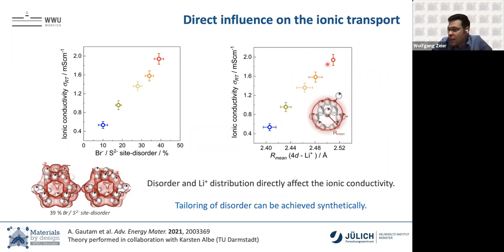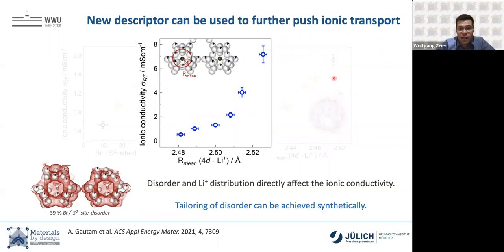And I was actually baffled by this, because oftentimes, at least in our community, we have the issue that one group may synthesize an ionic conductor and another group can't really match these ionic conductivities. And this happens to everyone. And the reason clearly is that even small changes in the synthesis procedure, be it that you didn't map out your furnace, or that the ampule that you reacted wasn't right in the middle, but maybe 5 centimeters out, so your actual synthesis temperature is wrong, or maybe you did quench it and it's not reported, small things that oftentimes we're not paying attention to can actually have a tremendous influence on the ionic transport in these materials. But by using this R mean, we can actually push the ionic conductivity to much higher values, and values that are in the end actually useful in cells.